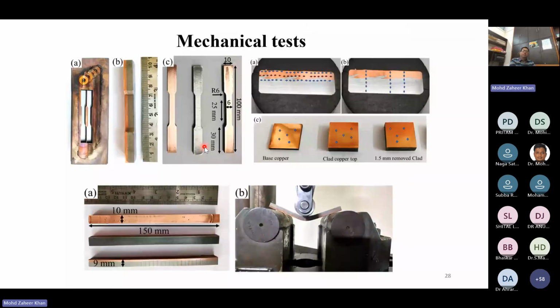After that, mechanical tests were carried out. So from the cladded layer, what we did is that tensile test specimens were machined out by EDM machine, and you can see. So once these specimens have been carried out, and if you look at the cross section of it, there is a copper layer on the top and a substrate at the bottom. Similarly, other specimens were also created only from the substrate and only from the copper, just to compare and see how they are behaving properly.